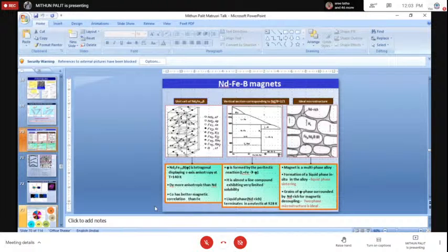If I look at the typical microstructure, it is a schematic one. On the right side cartoon, you can see that there are two phases. One is Nd2Fe14B, which is the white color there, and the matrix phase all around them is neodymium rich phases. And these neodymium rich phases should effectively encircle or wet all of these 2-14-1 particles. If it does so, then the 2-14-1 particles will not have efficient communication.